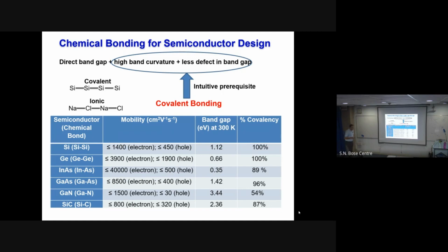So this is phonon limited mobility. I don't really understand what you mean by phonon limited mobility. Is this measured in a device, or in the bulk, where the limitation is just coming from the phonons at a given temperature, or is it measured in a device where you have other scattering, like surface roughness scattering or impurity levels? Because in silicon, for example, you never get 100 in a MOSFET. This number will be like half of that.